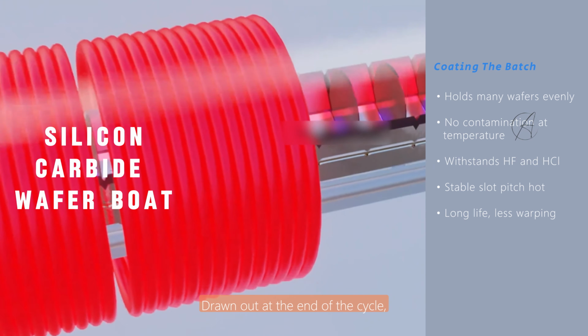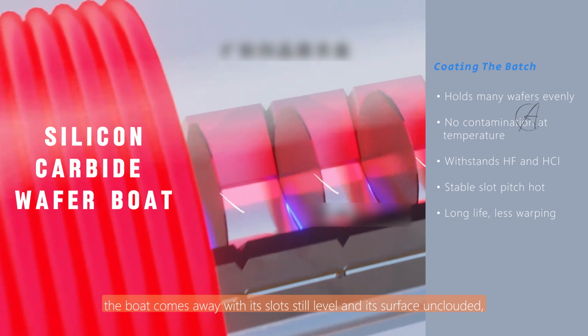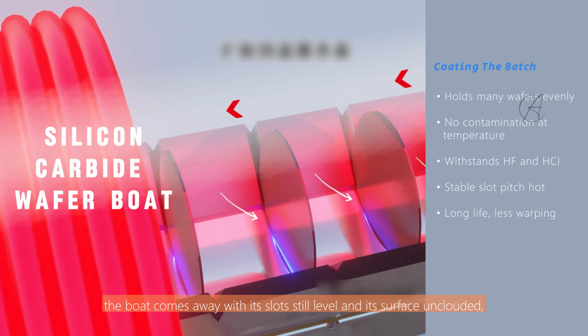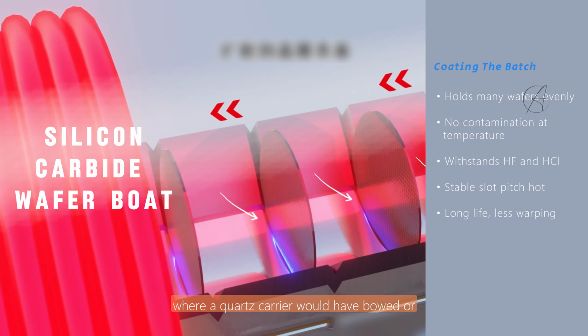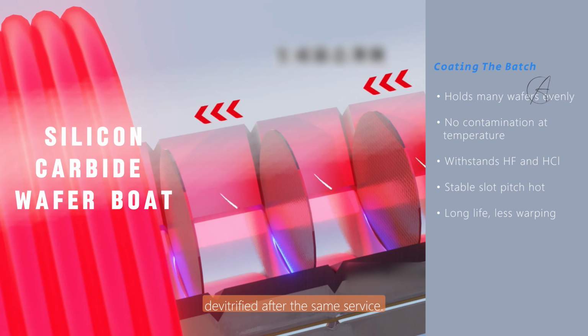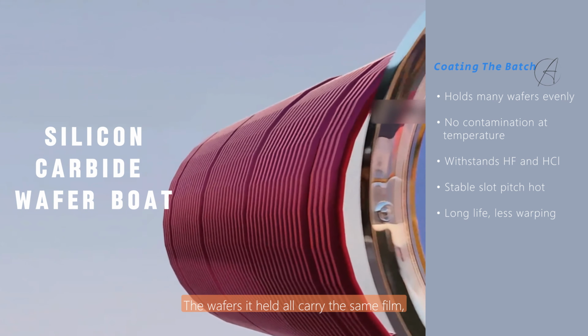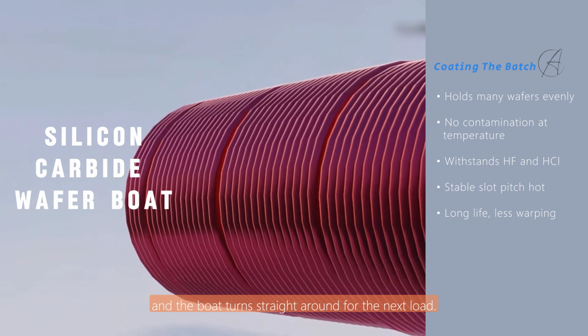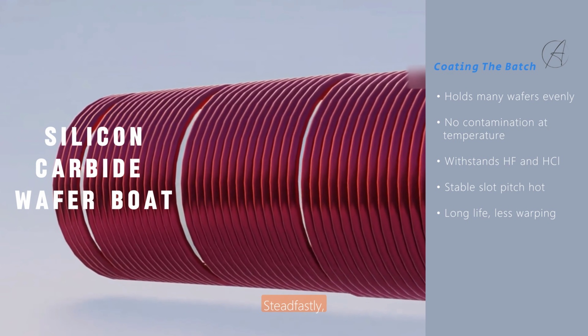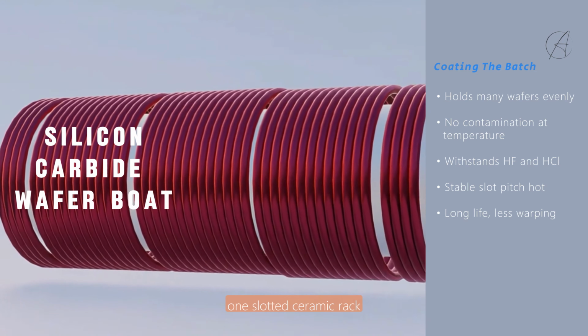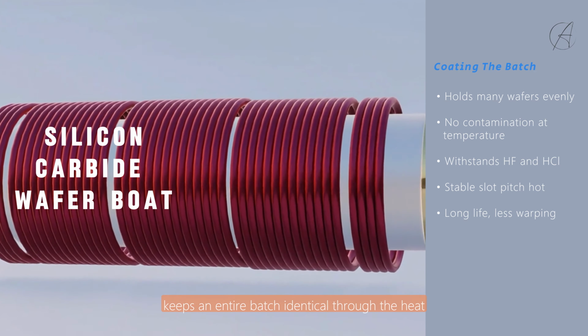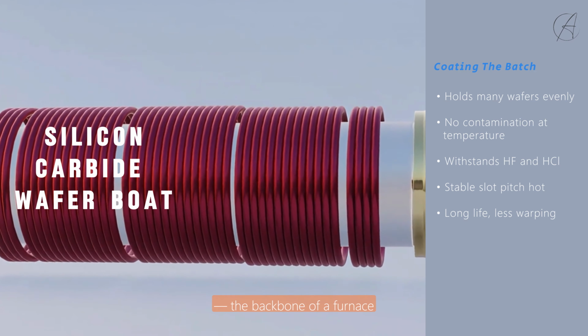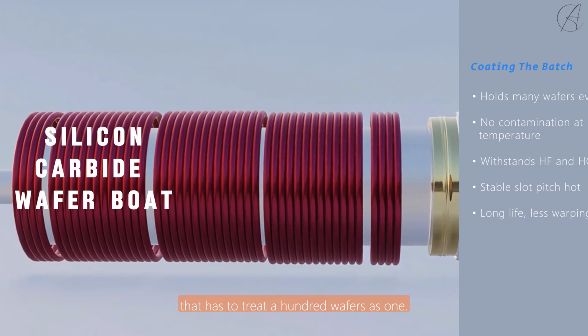Drawn out at the end of the cycle, the boat comes away with its slots still level and its surface unclouded, where a quartz carrier would have bowed or devitrified after the same service. The wafers it held all carry the same film, and the boat turns straight around for the next load. Steadfastly, one slotted ceramic rack keeps an entire batch identical through the heat, the backbone of a furnace that has to treat 100 wafers as one.